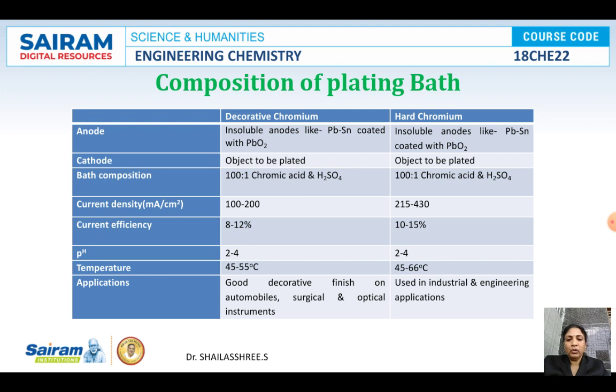So let us go to the composition of this plating bath. The anode here is an insoluble anode like lead or tin, which is coated with an alloy like lead oxide. Lead tin or lead antimony alloy, which is further coated with PbO2, is used here. That is the inert anode. And the cathode is always the object to be plated. What is the bath composition? What are the electrolyte contents here? It is chromic acid and H2SO4 in the ratio 100:1. Very important to mention this in your exams. The bath composition contains chromic acid and H2SO4 in the ratio 100:1.